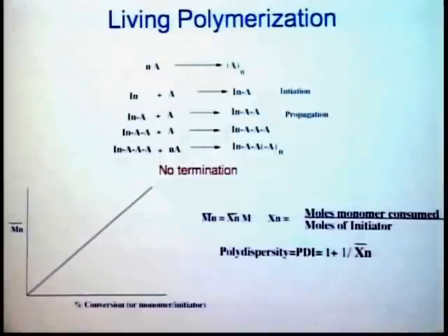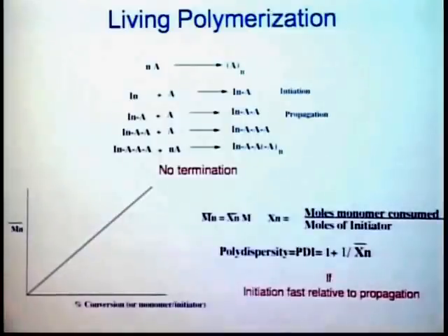And it turns out there's something else called polydispersity, which is related to the fact that when you grow a polymer, the chains grow in a random way. It's a random walk. And so you end up getting a distribution of molecular weights, which when you have a living system and everything is done right, is defined by a Poisson distribution. Okay? And that is if everything is controlled by statistics. And so we'll talk more about that in a moment.